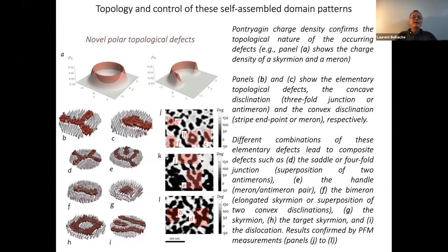For example, panel A is about a topological quantity, which is called the Pontryagin charge density. So its value is telling you what kind of topological object you have. Is it a skyrmion? Is it a meron? And also you can look inside your system and find very interesting objects. So when you go from phase one to phase five, for instance, that I told you before, these topological objects appear or disappear with some kind of puzzling pieces that when you put them together, you have a skyrmion or bimerons. For example, B is a concave disclination, C is called a convex disclination, and these can work together. For example, if I put two B together, you get a D, which is like a saddle four-fold junction. If I put B and C together, you get this handle called a meron and anti-meron. So a lot of different topological defects.